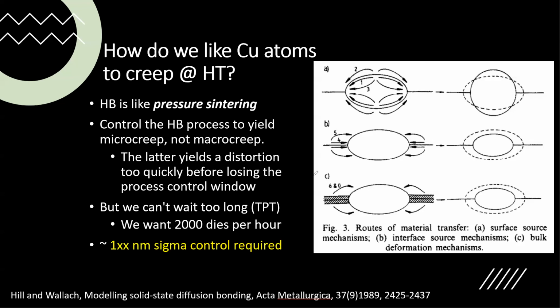Somebody did a comparison to pressure sintering, and they found there are three sources of material transfer, how the copper atom moves. One is the surface source, where the void initially becomes an oval shape. And then there are the interface source and the bulk source.